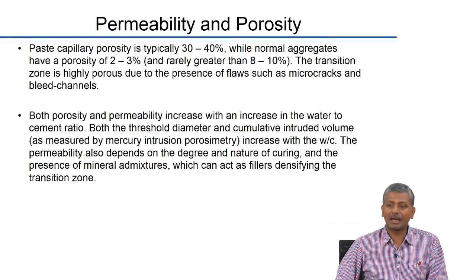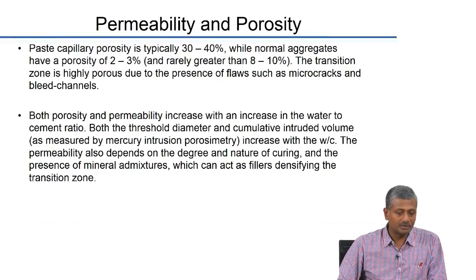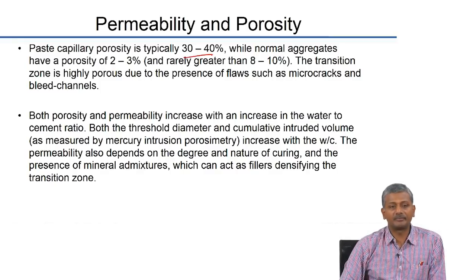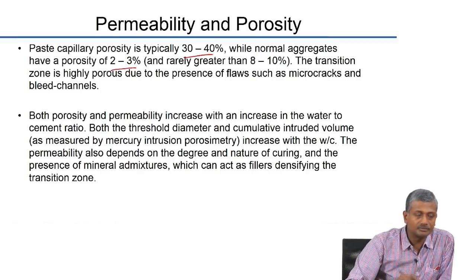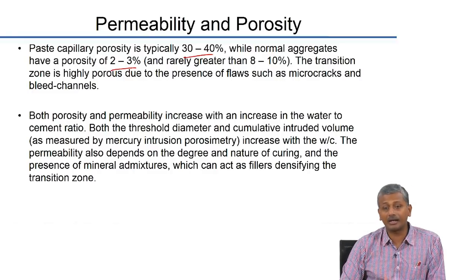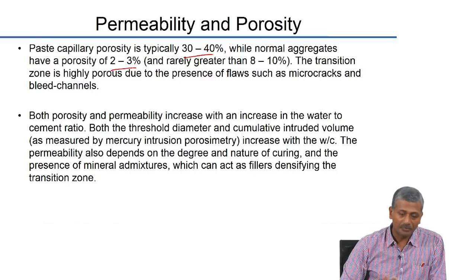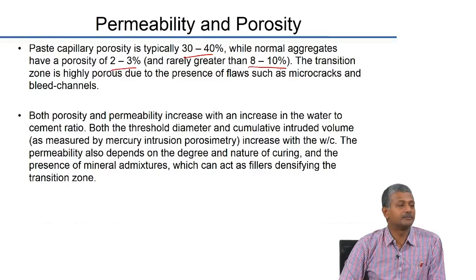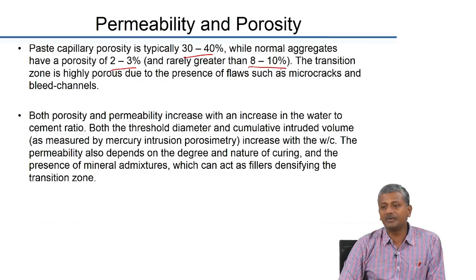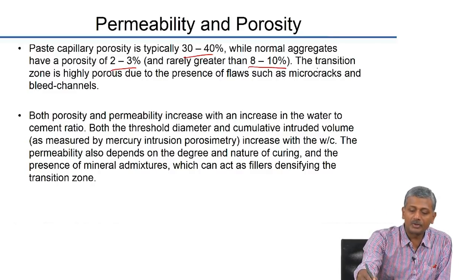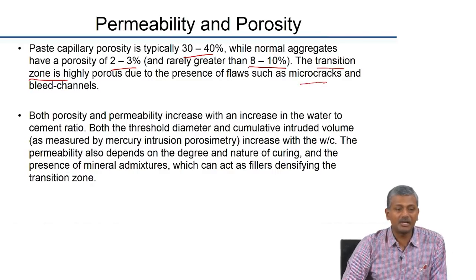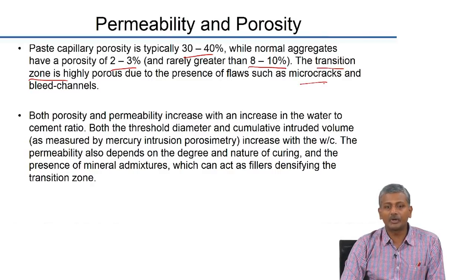Now, in general the capillary porosity of paste, when we talk about paste, we are looking at about 30% to 40% porosity, and aggregates only have a porosity of 2% to 3%. When you talk about granite and other aggregate, of course there are aggregates which may have higher porosities also, but rarely it is greater than 8% to 10%. So, we expect that when we study the permeability of concrete, the primary deciding factor for the permeability will be the ITZ, because it's got lot of pores and cracks and bleed channels inside the ITZ. Because of that, you can expect that the permeability of concrete is going to be much affected, even though the aggregate itself is not very porous.